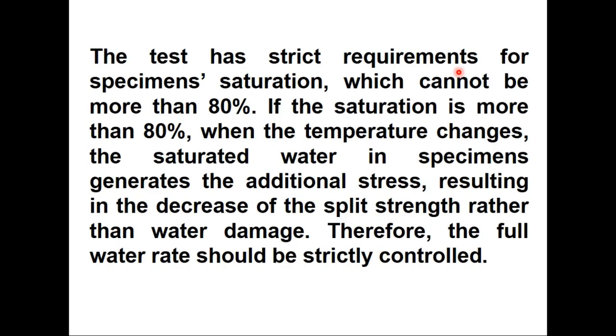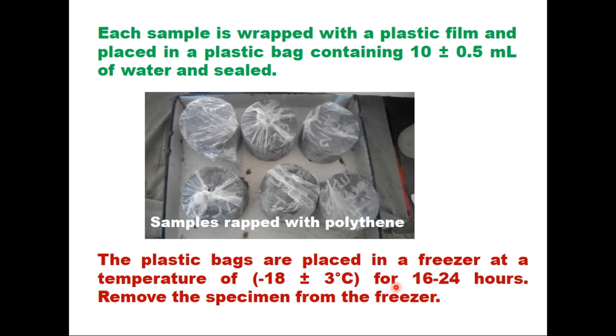This test has strict requirements: specimen saturation cannot be more than 80%. If saturation exceeds 80%, when temperature changes, the saturated water generates additional stress in the specimen, resulting in a decrease of split strength rather than water damage. The test is conducted to determine moisture susceptibility, and susceptibility cannot be correctly estimated if saturation exceeds 80%. Therefore, the saturation level must be strictly controlled. After that, each sample is wrapped with a plastic film and placed in a plastic bag containing 10 ml of water and sealed.